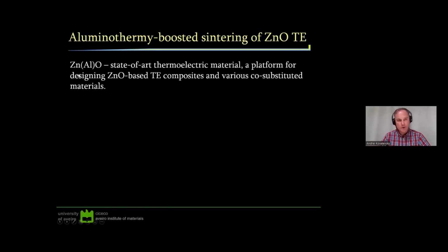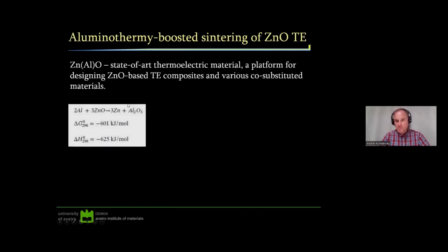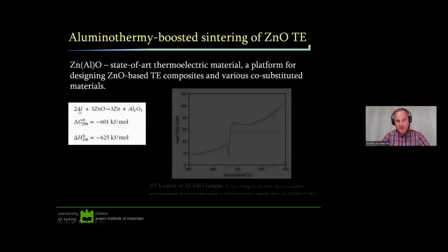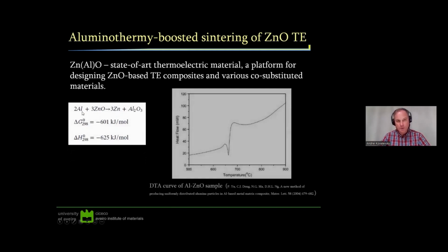One of those is in the case of zinc oxide doped with aluminum. This, if you don't know, is a state-of-the-art thermoelectric material and a platform for designing more complex, sophisticated thermoelectric composites based on zinc oxide. We can notice that the reaction between metallic aluminum and zinc oxide, the alumothermy reaction, is highly exothermic and can proceed even at room temperature. Of course, it doesn't proceed without reason, due to thermodynamics.